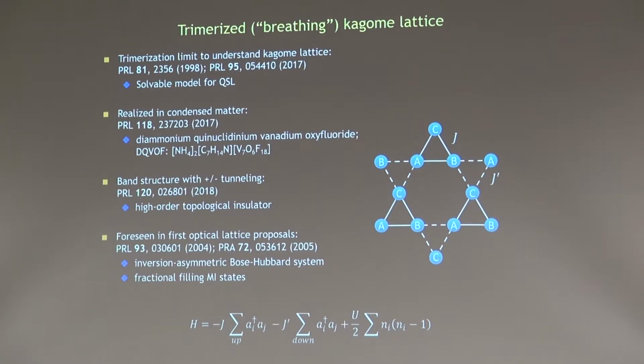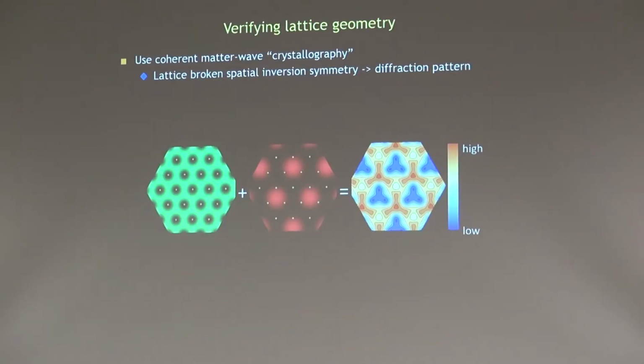There are some weirdly named crystals that also are described by the breathing Kagome lattice. I won't try to pronounce their names. And so anyhow, we've created them also in an atomic setting. One question was, how do we know we've produced this lattice? What's going to be really our signature? We're looking for a signature that reveals one of the key aspects of this lattice, which is the breaking of spatial inversion symmetry. So that fact that our up-pointing plaquettes are different than our down-pointing plaquettes. A standard way to look at crystal structure in solid-state physics is to send coherent X-rays through the crystal and look at diffraction. We're going to follow a similar tack. We're going to send coherent matter waves through this lattice to try to see the structure of the underlying lattice.